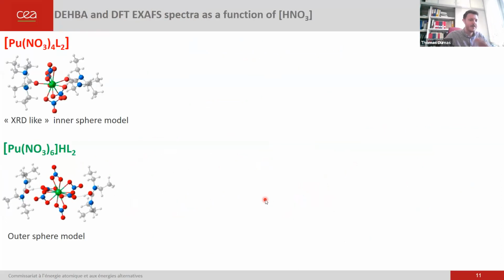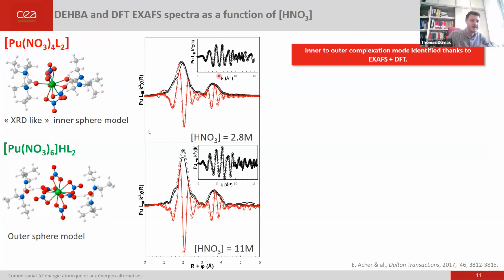So let me go back now to the effect of acidity. We have these 2 models that work pretty well. One is working quite well if you compare the simulated spectra, which is the open circles here, to the experimental data that we measured at lower acidic condition. And if we compare what we obtained for the higher acidic condition, now we have a model which is the outer sphere complex with 6 nitrate ligand that works pretty well.